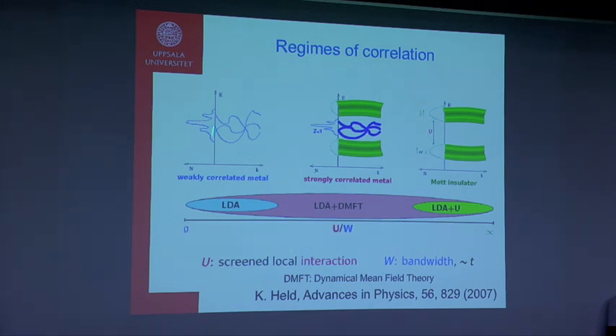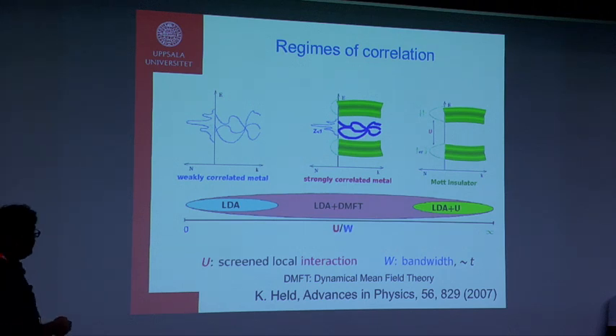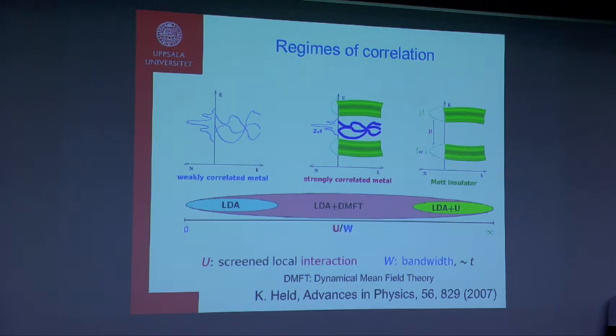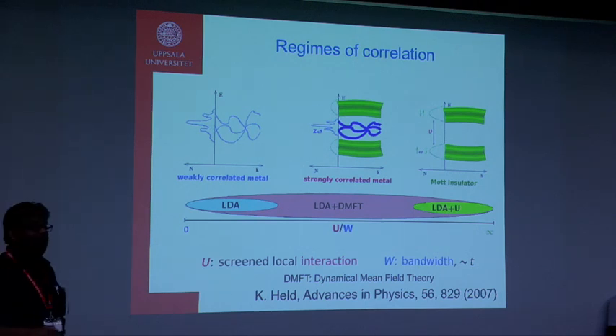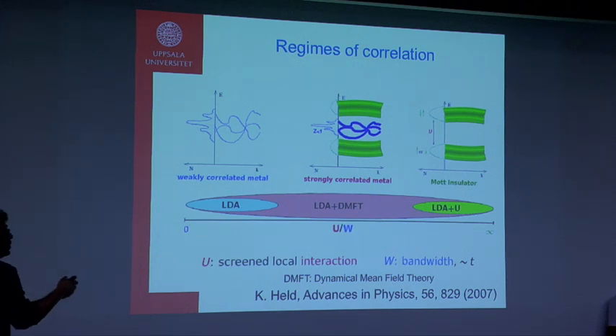So on the left hand side, LDA is good enough, weakly correlated metal. On the right hand side, LDA plus U is good because the electron correlation is very strong. The problem is that when something is in the middle, that gives us a lot of problems, which is a strongly correlated metal. So you have strong correlations, but also a metal. In this case, you have the lower Hubbard band, upper Hubbard band, but also a quasi-particle peak that is coming in between, close to the Fermi level. This you cannot get with LDA plus U. So you have to go beyond your static mean field theory to capture this effect,